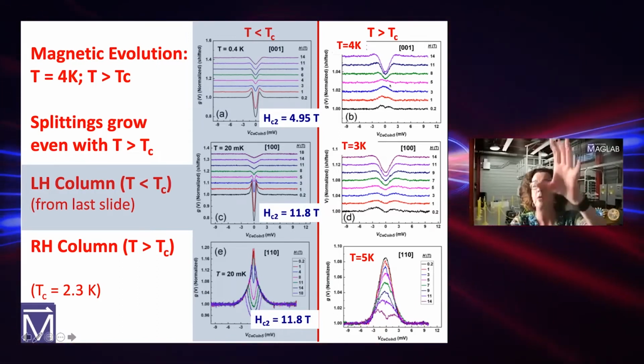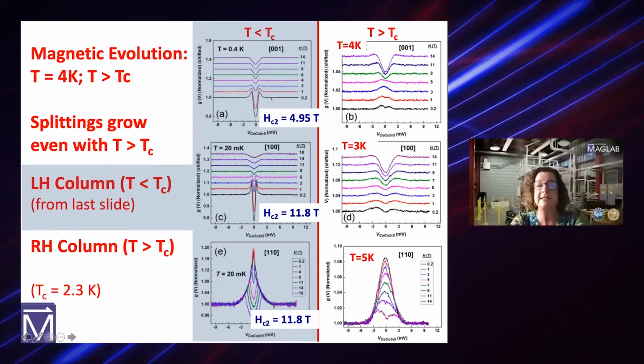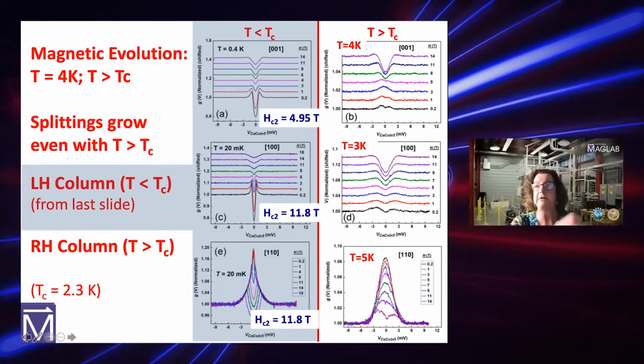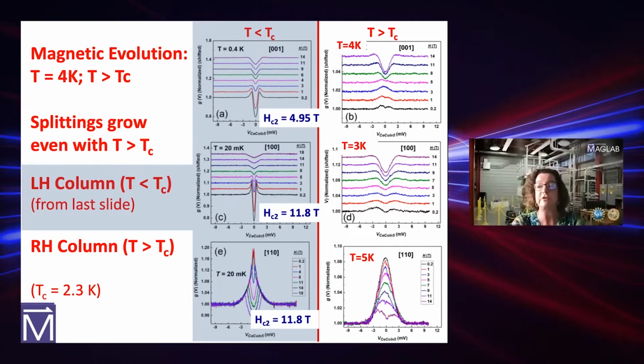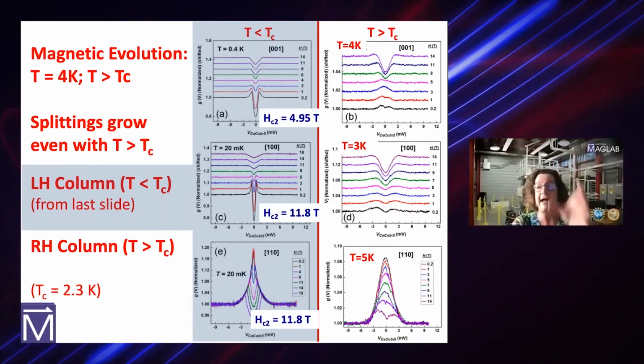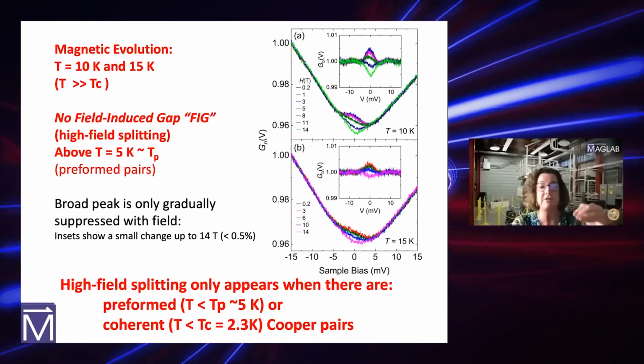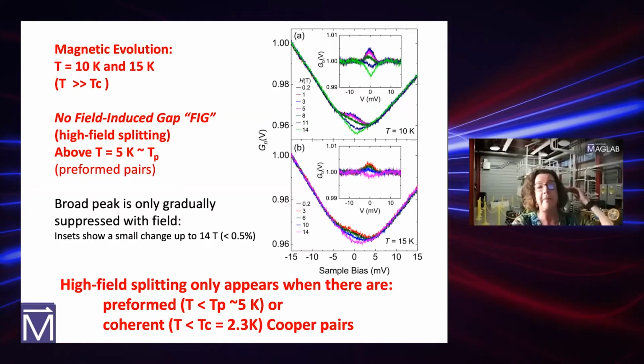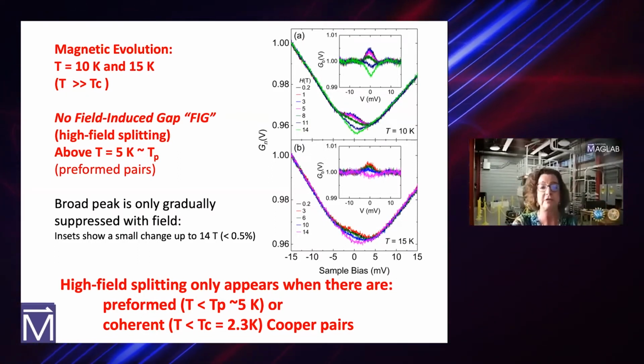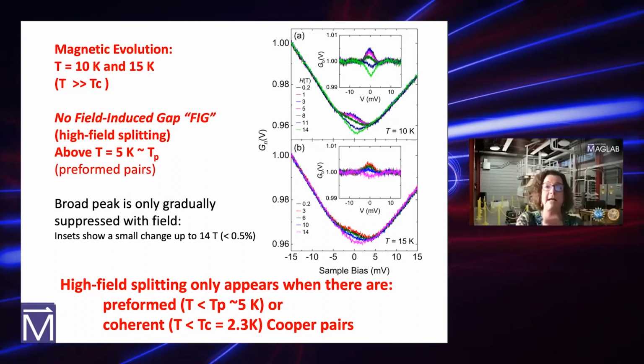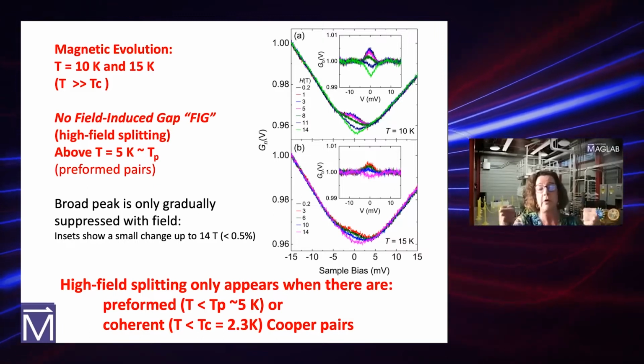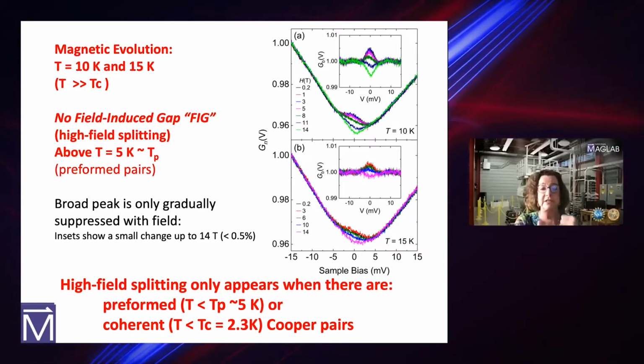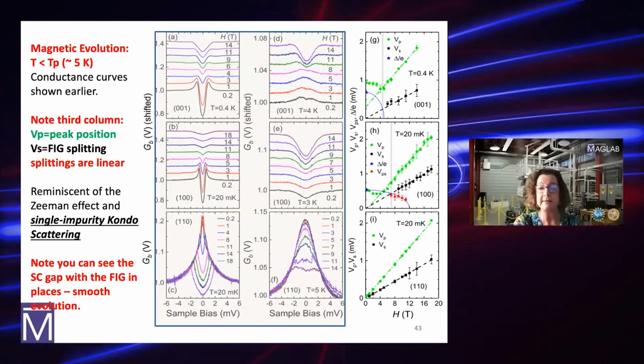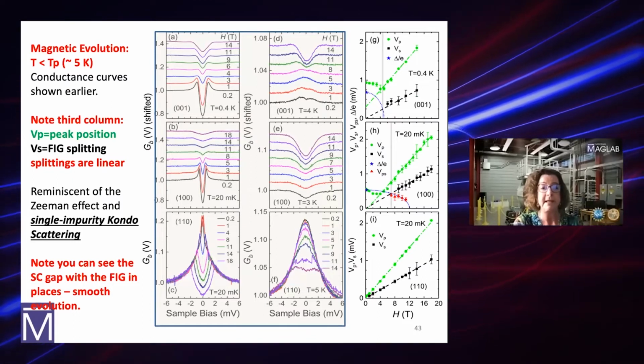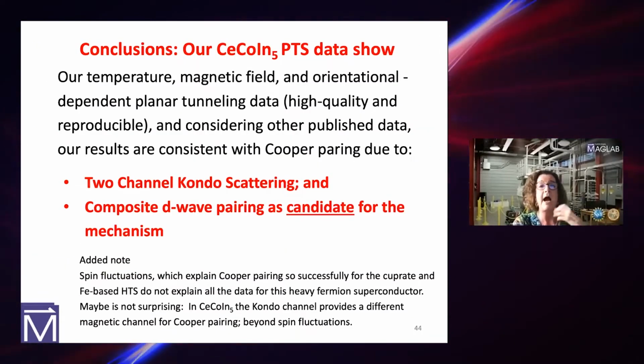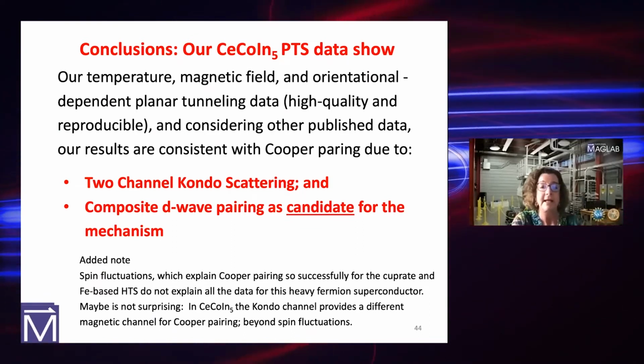Now, hold that thought. When you're in the pre-formed pair range, when you're below TC, when you have coherent pairs or incoherent pairs, increased field gives you a field-induced gap that grows with applied field to the highest fields measured. If we go above that temperature, these are data taken at 10 and 15 K. If we're above the preformed pair temperature, there is no field-induced gap. In other words, you need to have some kind of Cooper pairs there, either preformed pairs or coherent pairs, to get a high field-induced gap, okay?